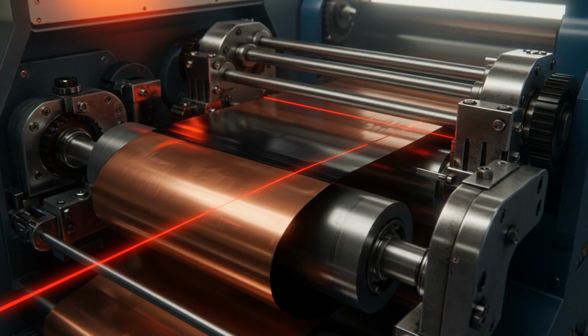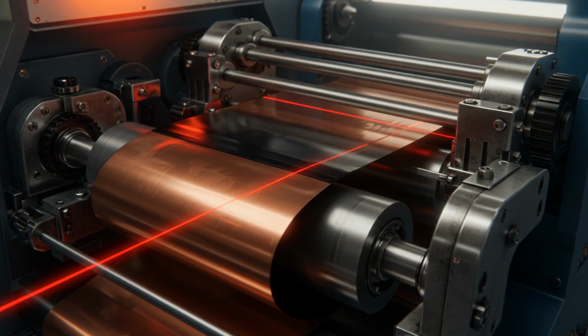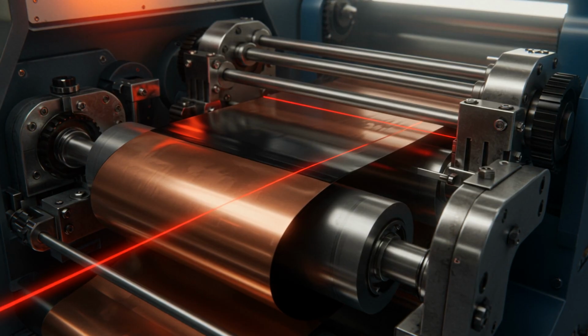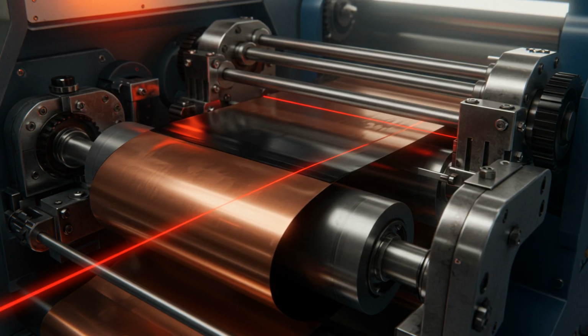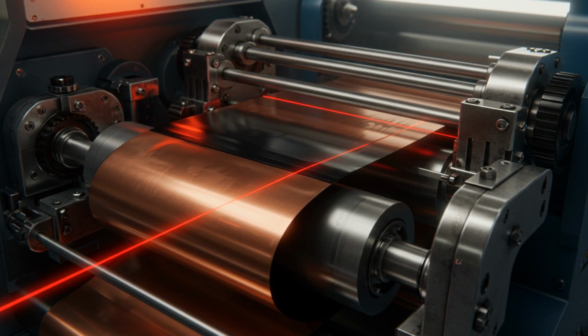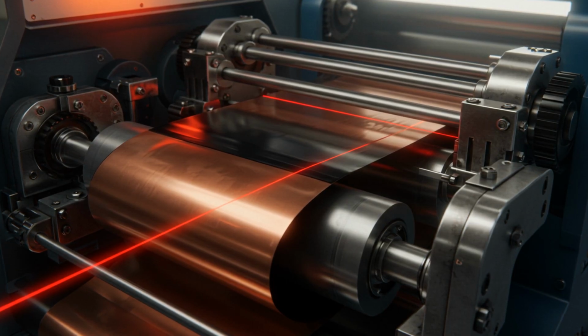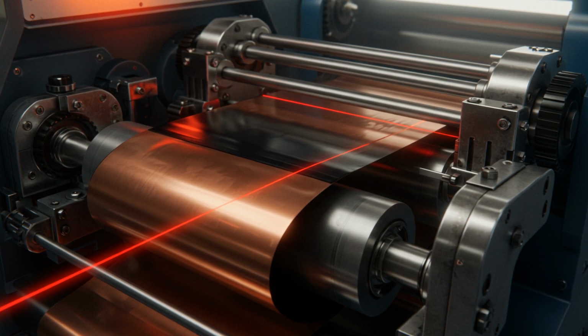Now, the liquid slurry must become a solid component. This happens on the coating line, a machine hundreds of feet long that operates with the precision of a Swiss watch. Ultra-thin foils of copper for the anode and aluminum for the cathode are unspooled at high speeds. As the foil zips through the machine, high-precision slot dies apply the slurry at a thickness of exactly 100 micrometers. To put that in perspective, that is roughly the width of a single strand of hair.